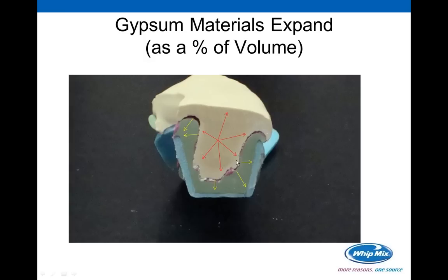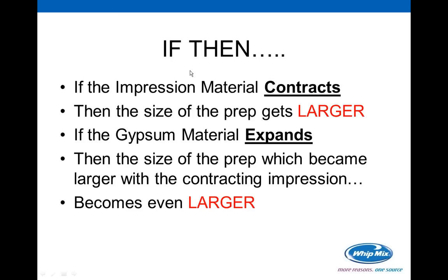What we should be using are low expansion stones, unless you have determined that you specifically need more room. And that would be based on perhaps doctor preference. Let's do an if-then. If the impression material contracts, then the size of the prep in the impression gets larger. If the gypsum material expands, then the size of the prep, which became larger with the contracting impression, becomes even larger. So if you're fighting that larger battle, you're going to have to look at using smaller expanding die stones.